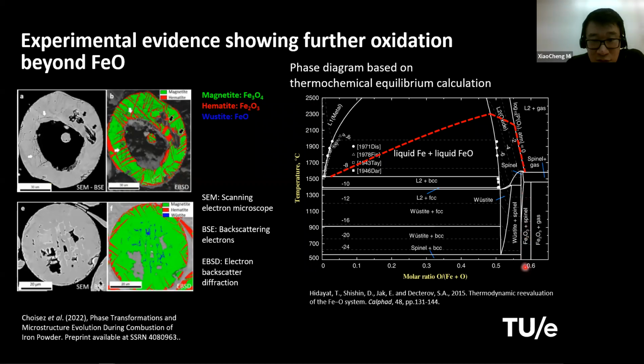But if you follow this saturation boundary, you can see that it's actually beyond the stoichiometry of the spinel, or the magnetite. So that means if you get to this point in the liquid phase and get solidified, the particle actually contains more oxygen than is required to form Fe3O4. And what happens next is the particle needs to expel this oxygen, right?